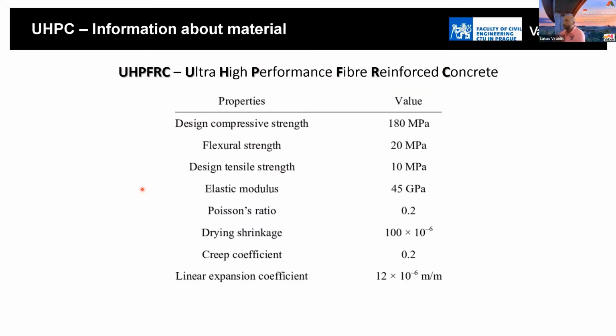On this slide, you can see typical material properties of UHP FRC, that means ultra high performance fiber reinforced concrete. We add fibers to the concrete mass. Design compressive strength is, as I said, more than 150 megapascal. In this case, we obtained 180 megapascal.